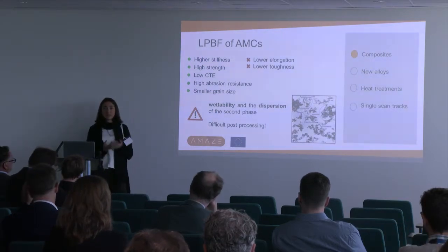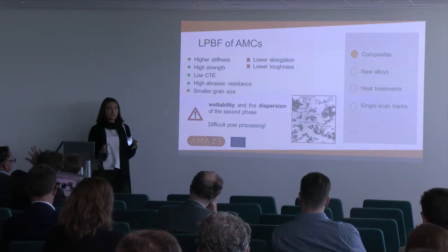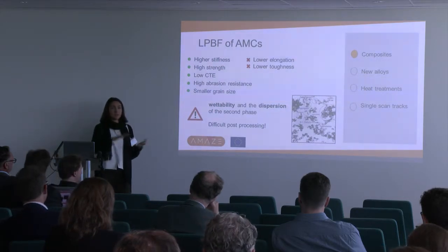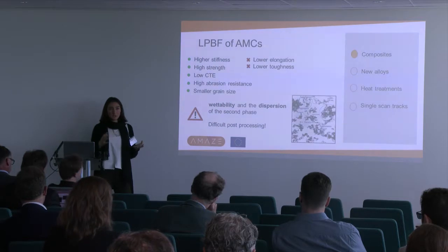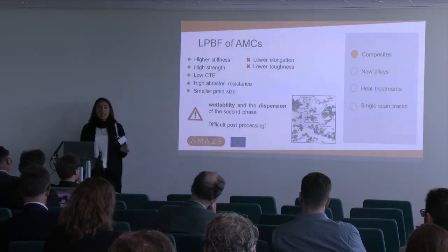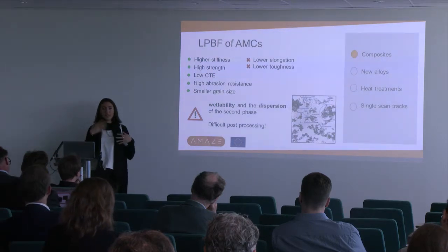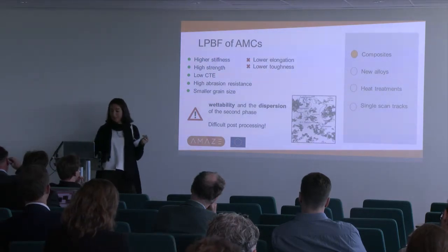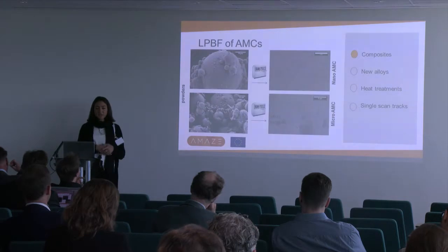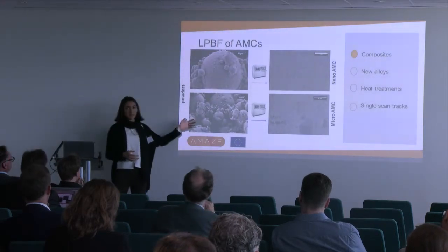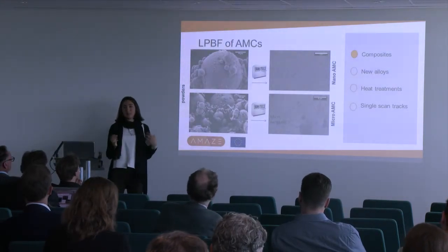So it would be really interesting to produce composites with a homogeneous dispersion, because the layer by layer process allows us a good dispersion of the particles, and in a near-net shape component, so we can reduce the post-processing steps. So this was the idea. And so we thought about producing nanocomposites and microcomposites. We started simply by mixing powders.